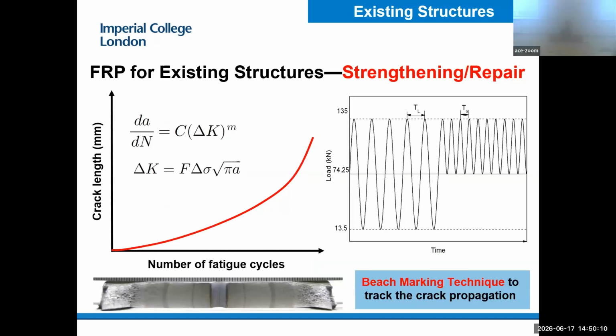The vertical axis is the crack length, the horizontal axis is the fatigue cycles. This is called a fatigue crack propagation curve. However, because the surface of the steel plate is attached with FRP laminate, you cannot see the propagation of the crack - it's covered by this FRP material.